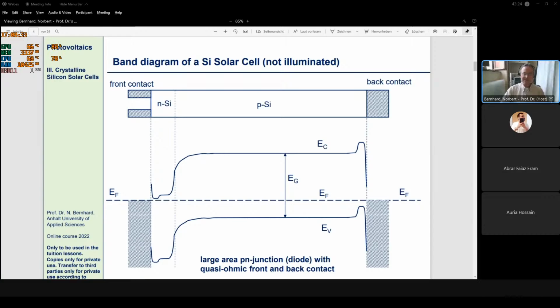If this barrier is very narrow, the charge carrier can tunnel through it, and basically the barrier is not seen by the charge carriers. And that means that the contact appears as if it were ohmic, and such a contact is called a quasi-ohmic contact. That means one should always be aware. I mean, usually in semiconductors, what one calls an ohmic contact, that means just with an ohmic current-voltage behavior, in reality is usually a very narrow Schottky barrier. Okay, this is just a side comment for the experts among you.